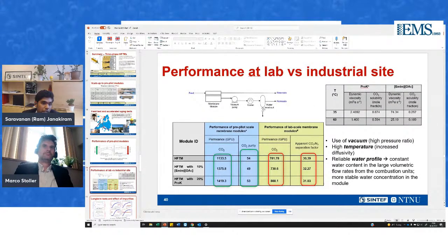And that's what we actually saw in the system, where here I've written that the EMIM acetate, for example, the reason why we have written this, I did not highlight this, of course, in the presentation because I did not have time. But if you look at it at 35 degrees Celsius, you have the viscosity of the ionic liquid to be 74, which is quite high. It's quite viscous. But then at high temperature, they become really less viscous, which means they become more mobile. So that's one of the reasons why we are adding these mobile carriers, because we want them to be more mobile at high temperatures so that you get the maximum CO2 out of the system. And that's why we have an increased performance up to 1,400 GPU when the actual membranes in the lab were only up to 730 GPU.